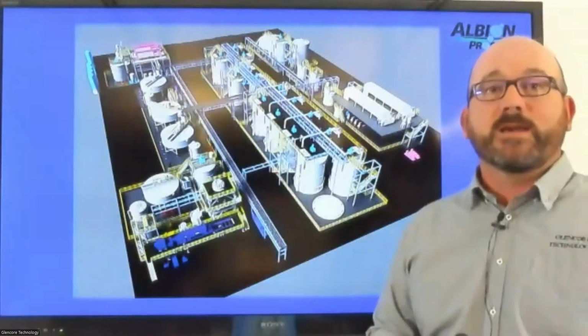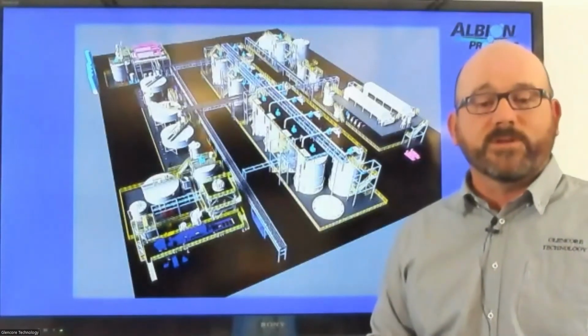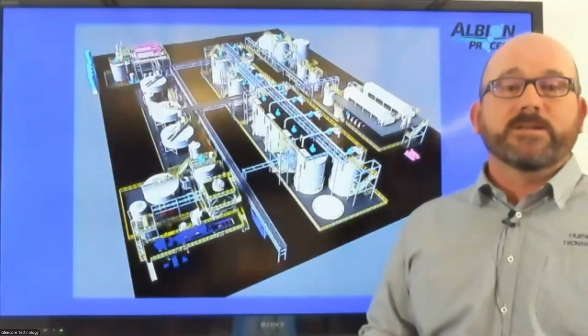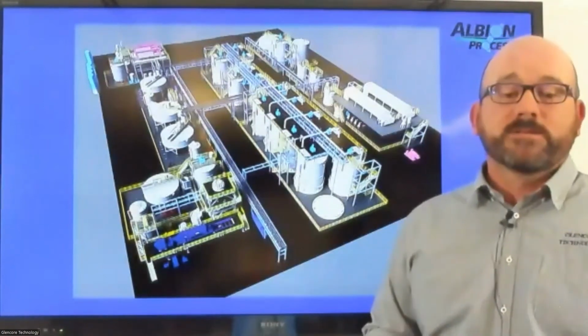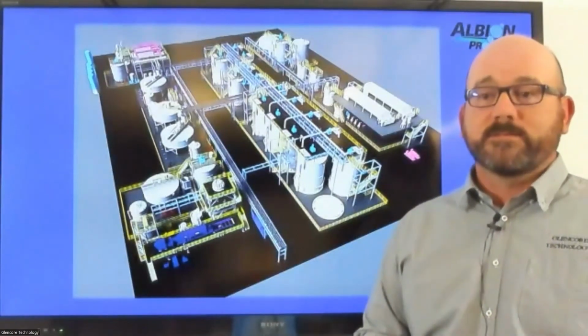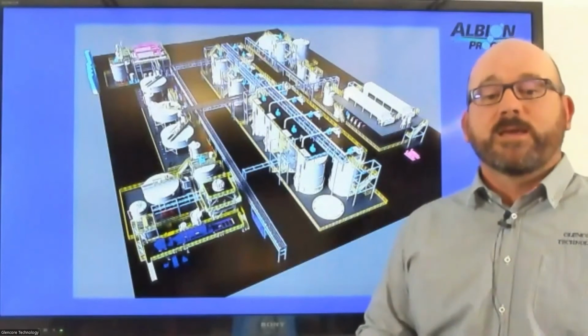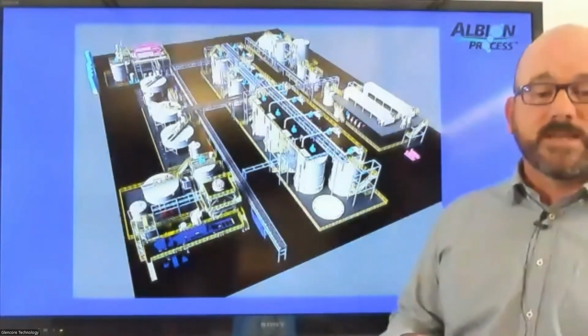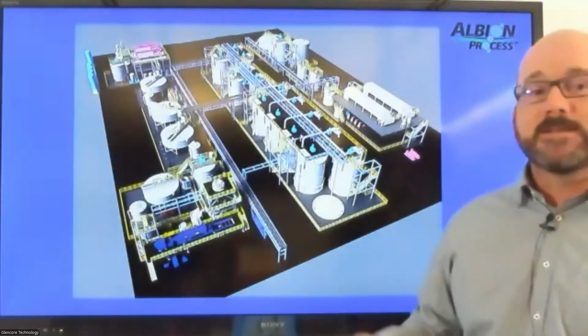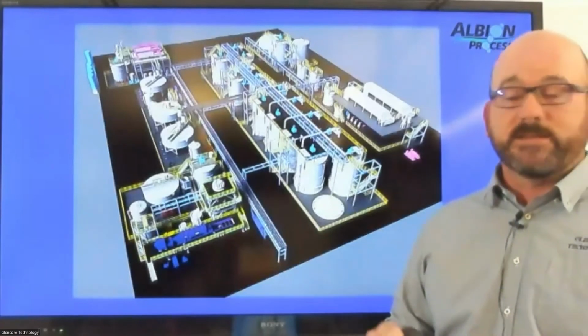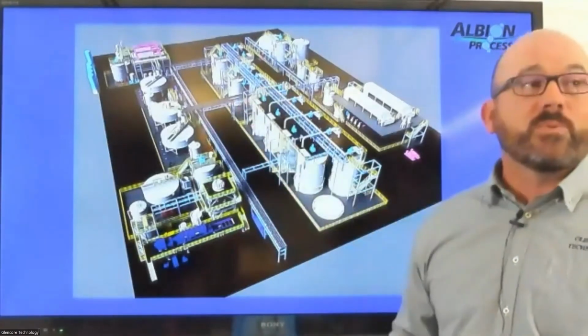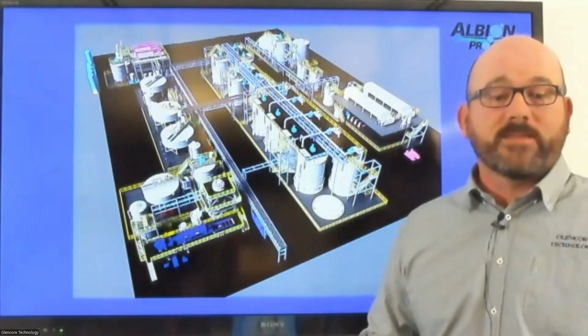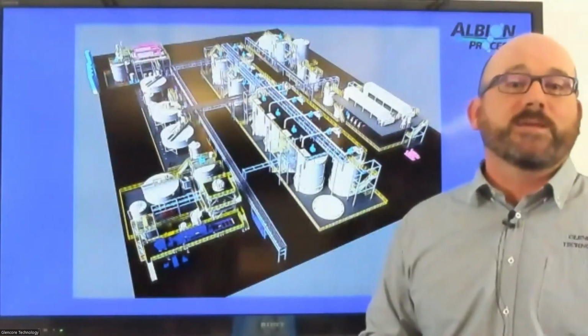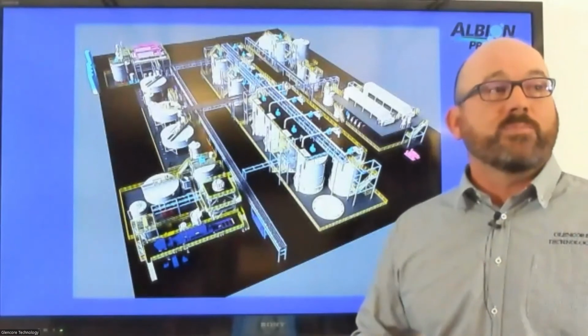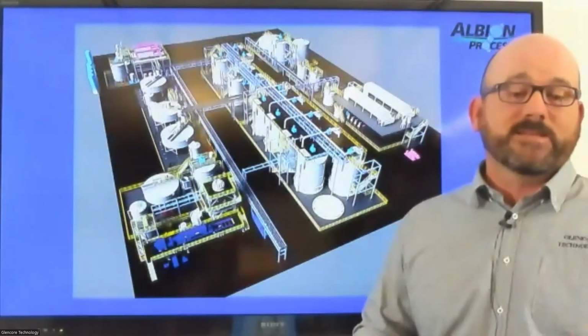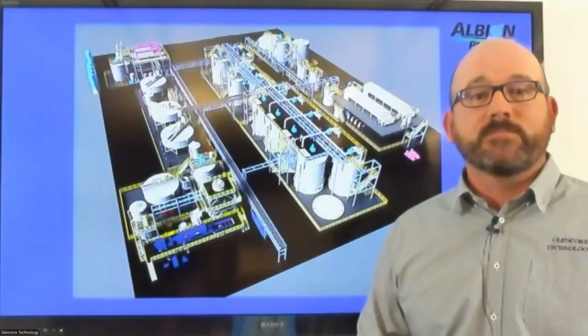So lifting the pH up to 3.5 to drop out the iron and aluminium prior to solid liquid separation. Then taking the PLS out for our base metals, and taking the residue from that forward. Here we're going into a lime boil in this circuit using another Albion leach reactor, elevating the pH up to pH 10 to run the lime boil, because it was found that in this case it assisted in the gold recovery downstream.